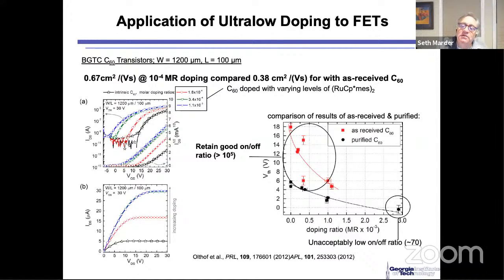So here, what the dopant is doing is taking something that, if you did elemental analysis on the as received C60, would look really good. But as anyone who's worked in the area of organic electronics knows, in many cases, the electronic properties are truly a much more sensitive indicator of material purity than things like elemental analysis or mass spec, because carriers at the level of 10 to the minus 3% are a hell of a lot of carriers to change the electronic property. But if you measure elemental analysis, your uncertainties are much greater. With NMR, you can see percent, maybe tenths of percent, but very small levels of impurity are hard to detect.